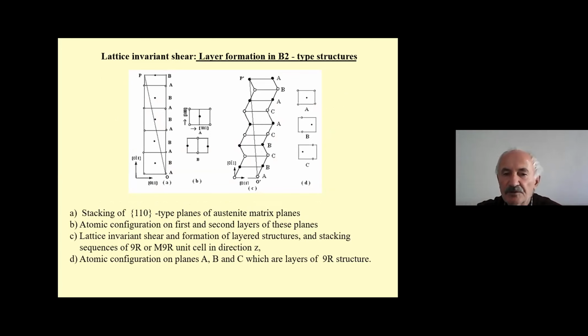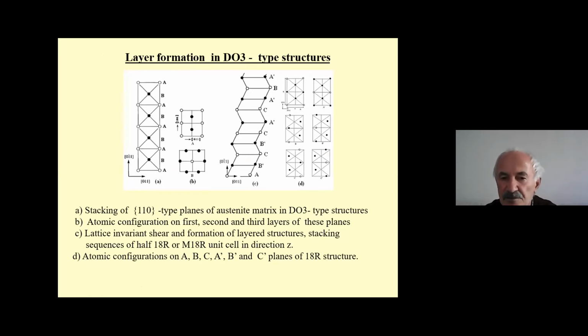These are the formation of the layer structures. This is the stacking of 110 type planes of the austenitic matrix. This stacking is AB, AB, AB, AB. With the lattice invariant shear, this stacking turns into this stacking: AB, ABC, BCA, CAB, and A for 9R martensitic structures. Also, as you can see, the product phase exhibits layered structures. This is another illustration of the formation of layered structures for DO3 type parent phase structures.